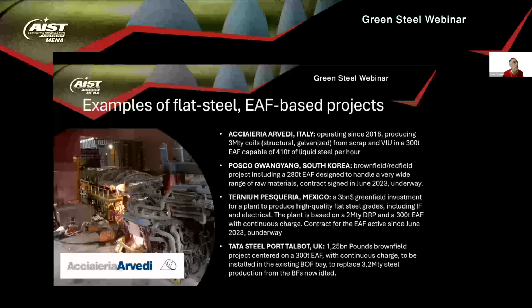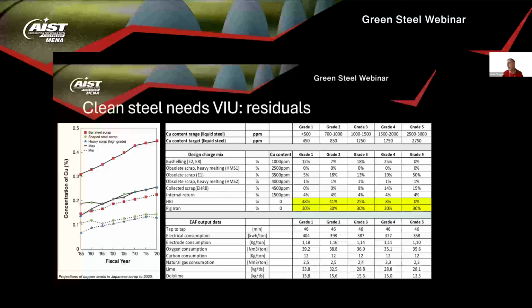The trend in Europe seems to be based mostly on the obsolescence of the productive assets. When the time for the relining of an old blast furnace comes near, the steelmaker has to take a decision. Most of the steelmakers facing this decision in Europe are deciding to kill the blast furnace and go for something else. Then the next decision is to what extent to push the integration upstream, because every producer of high quality steel grades knows that it's impossible to produce them with scrap alone. As of now, it's impossible to chemically remove the copper, for instance, or the tin from the liquid steel. There are studies being done of electrolytic processes to remove carbon and copper.